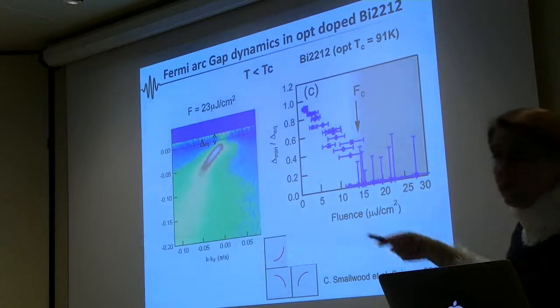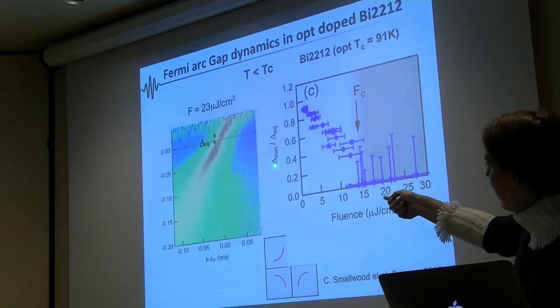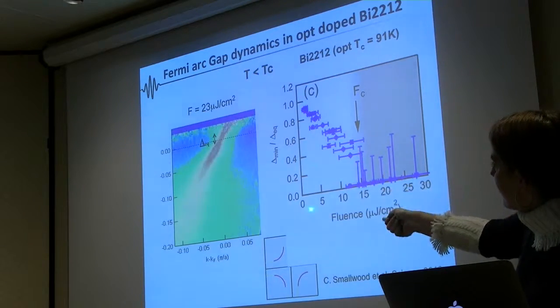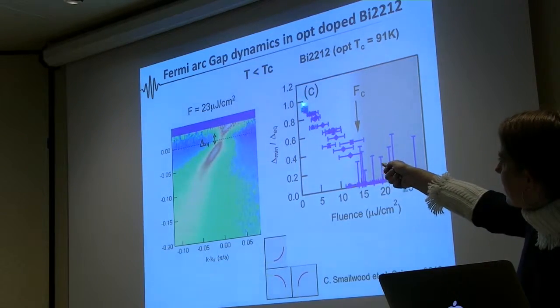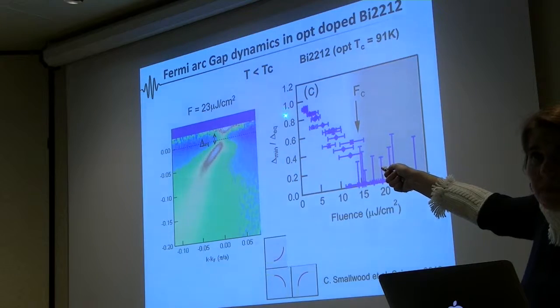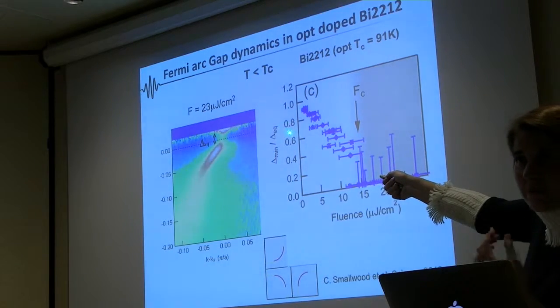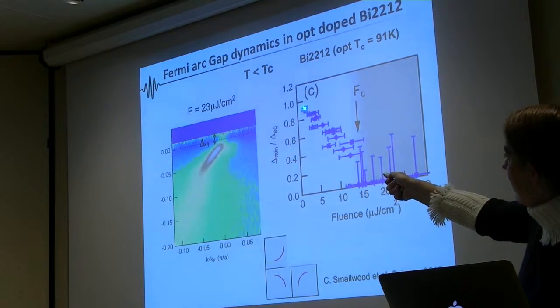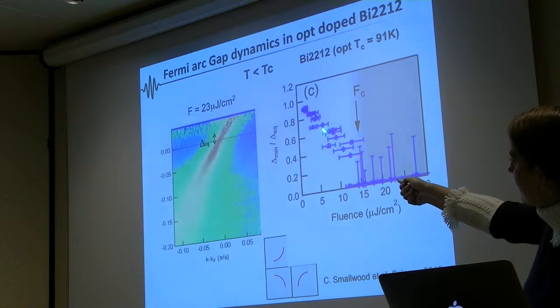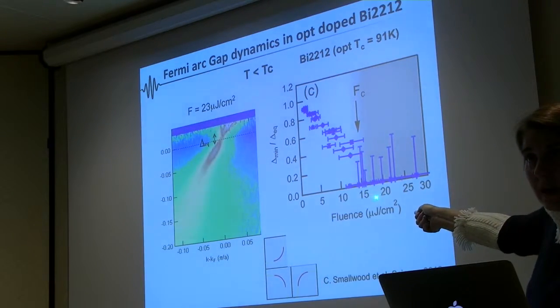Then you are not able to close the superconducting gap. And this is summarized here. You see that as a function of fluence, for very low fluence, this is pretty much close to 1. So you are sending energy to the system, but you are barely affecting the superconducting gap. But as you increase the fluence, eventually you can completely close the gap.